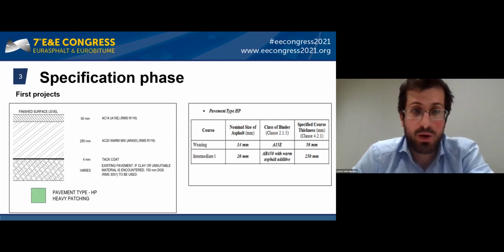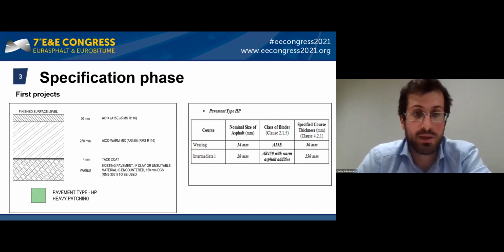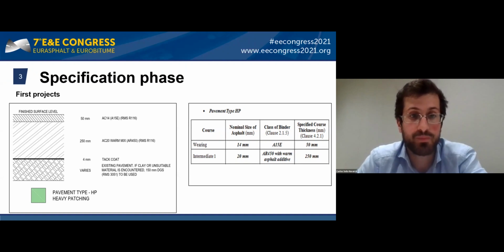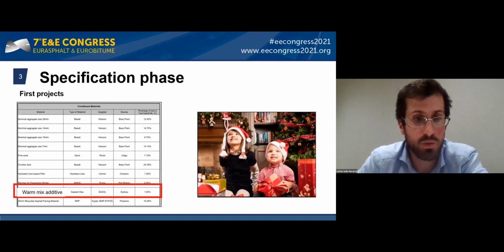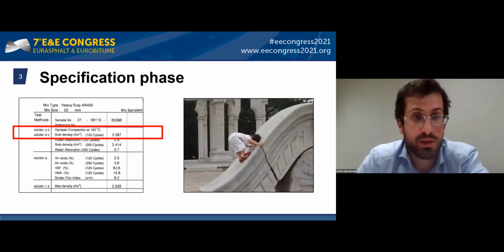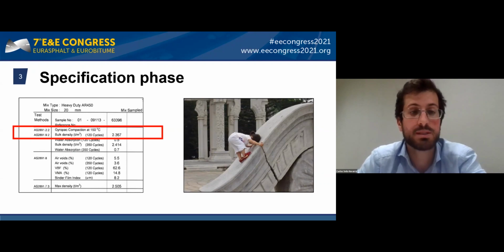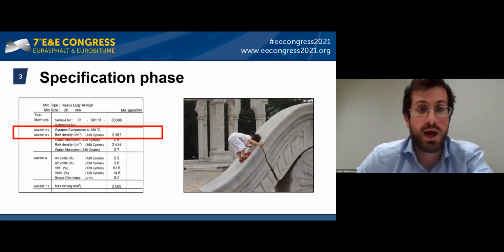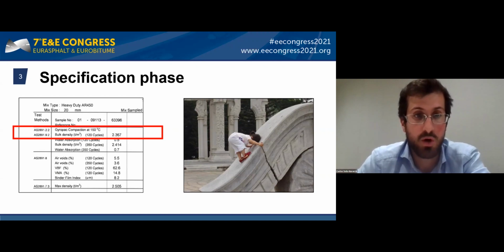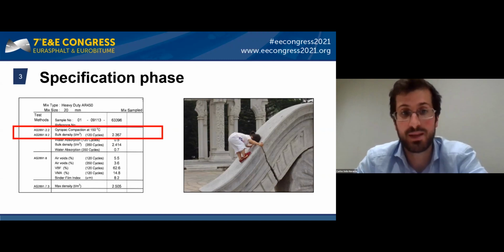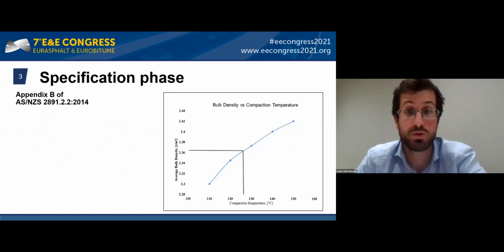At the beginning of the program, we thought that just adding the word Warmix to the right of the type of mix, AC20, was sufficient, along with adding the requirement for Warmix in the specification. And it was quite promising, as we were receiving the constituent material report with the Warmix additive in it. However, when we were reviewing the laboratory test reports, we could see that the compaction temperature of the asphalt mixes was still 150, similar to a hot mix. Therefore, there was a lack of communication or understanding from the contractor and supplier of the intent of the use of Warmix.